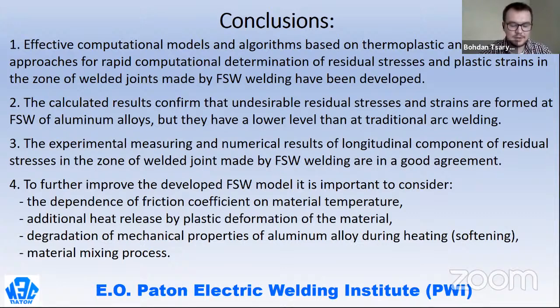Also, experimental and calculated data have a good agreement, and in the future I want to research the dependence of friction coefficient on material temperature, and also additional heat release by plastic deformation of material, degradation of mechanical properties of aluminum alloy during heating, and also material mixing.